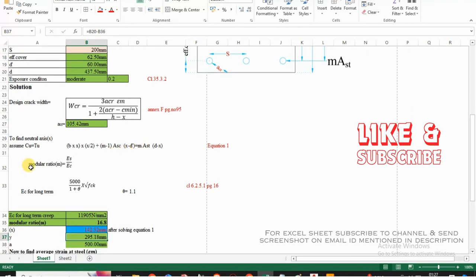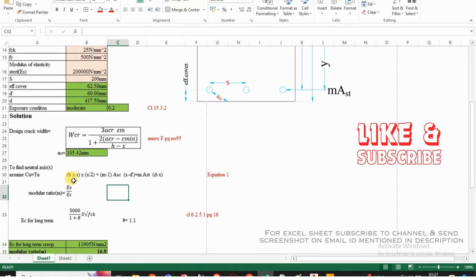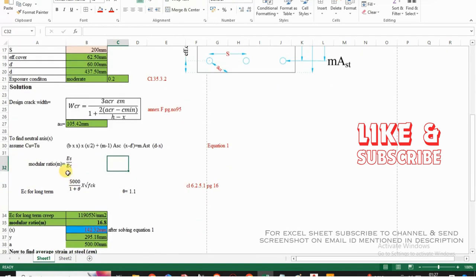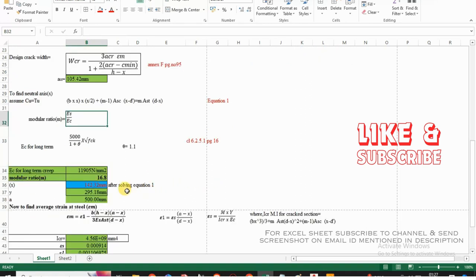For that we will need the value of m, that is modular ratio, equals modulus of elasticity of steel upon modulus of elasticity of concrete. Now modulus of elasticity of concrete as per clause 6.2 of IS code is 5000 under root fck, but for long term creep we have to add 1 plus theta in the denominator. That is 6 days, 28 days and 1 year. We'll consider 1 year.